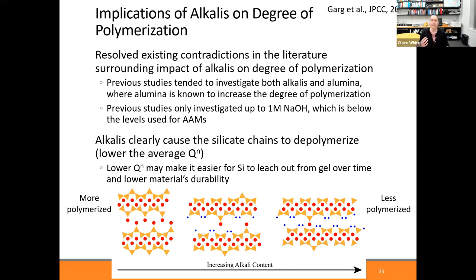addition to have if you're going to have sodium coming at the same time, which means when you're making concrete, if you're trying to reduce the amount of Portland cement powder and you're using something that has sodium in it, you also want it to have reactive alumina in there as well.